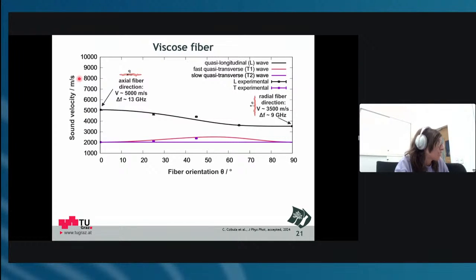When you do this evaluation and plot these solutions of the Christoffel equation, as I've shown you before, you get these curves over the fiber orientation. The points are the measurements that I have taken, and you see the longitudinal wave is fitted very well. Down here the two are very close together in frequency shifts, so it would be very hard to distinguish them. Transverse phonon modes are really tricky. We go from around 13 gigahertz with the longitudinal phonon mode down to 9 gigahertz. So the sound velocity goes from 5,000 meters per second to 3,500 meters per second when we have done 90-degree alignment, or measured just the radial fiber direction.